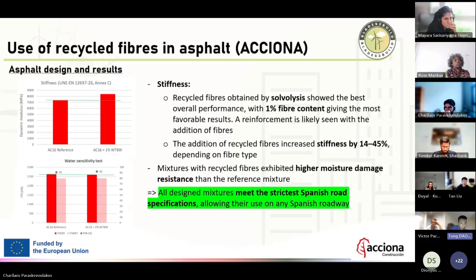And then in terms of mechanical behavior, here we talk about the stiffness. Stiffness is the elasticity modulus at fixed frequency and temperature, I think it's about 15 hertz at 10 degrees Celsius, or 15 degrees Celsius and 10 hertz. They see an improvement in terms of stiffness, meaning that with 1% of wind turbine blade waste, we have stiffer asphalt at the same testing conditions compared to the ordinary asphalt. And they thought that thanks to the 1% of wind turbine blade waste fibers, they got a reinforcement like the fibers in the concrete in this case.